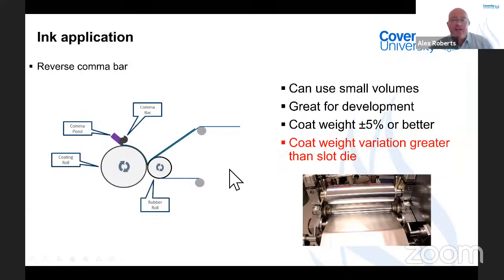So there are various technologies that you'll find in these reel-to-reel coaters. You just saw there a reverse comma bar coater setup, which is what I work with in my laboratory. And you can see we have a pond where the ink will be put into, and then a comma-shaped bar will lift and a coating roller will take the ink and flatten it out. And then you transfer this onto a foil that passes in the other direction and then goes into an oven.